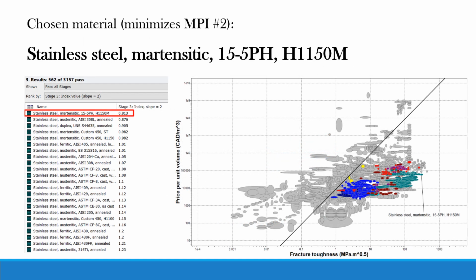At this point, we determined that the fracture toughness of the material was the more important constraint, as it determines the stress required to pose the risk of the cylinder leaking. So, we decided that to account for the crack propagation, the material with the lowest value of the second MPI would be chosen, which resulted in selecting 15-5 PH martensitic stainless steel in the H1150M condition.